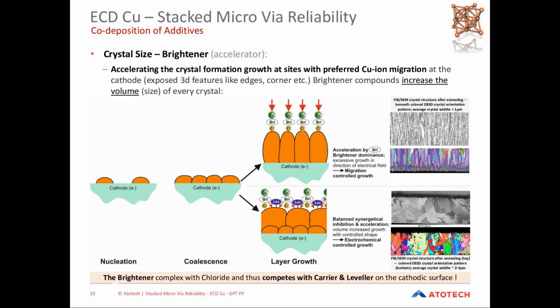The next will be the brightener, which usually accelerates the copper deposition, which will lead to very rough copper plating if you use a brightening compound alone as an organic additive. Only in combination with a leveling compound will you get the desired crystal structure and smoothness. You will get larger crystals with an increased ductility, but still crystals which are uniform and polygonal shaped to prevent any roughness.